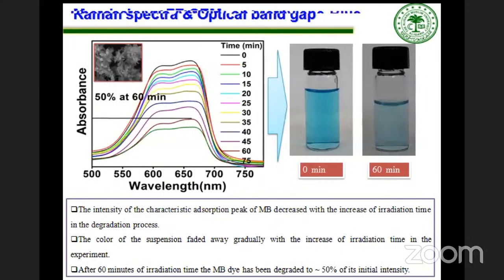And from an application point of view, we performed the degradation of methylene blue dye with irradiation of UV visible light on the solution, which contained our titanium dioxide nanorods. This figure shows the result of degradation of methylene blue dye at different time intervals from 0 to 75 minutes. It was observed that after 60 minutes, more than 50% of the dye is degraded.